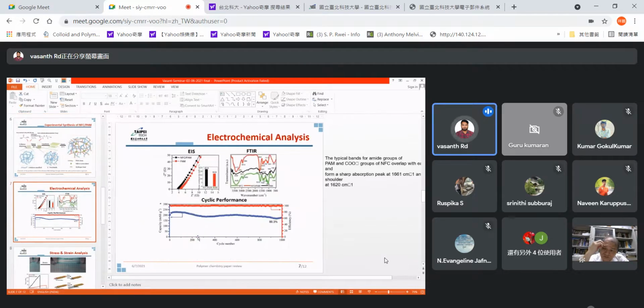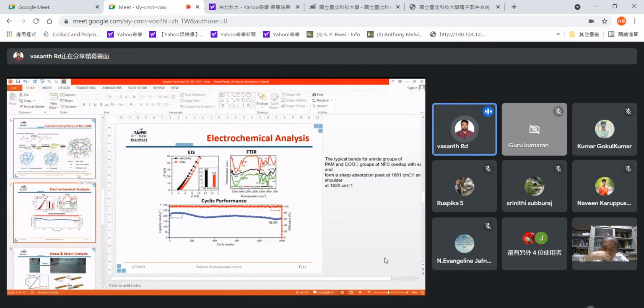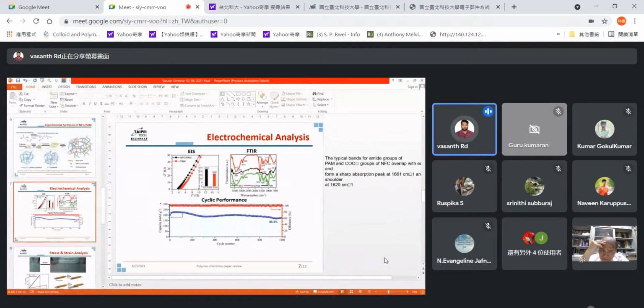So this is the electrochemical analysis, in which the EIS data shows the high conductivity of NFC PAM when compared to the conventional PAM. The conventional PAM is fabricated using deionized water in order to compare the data with the nanocellulose PAM, and the FTIR data. In the EIS data, it is clearly seen that the NFC PAM has a high conductivity of about 22.8 Siemens per centimeter when compared to the conventional PAM, which is about 16.9 Siemens per centimeter.